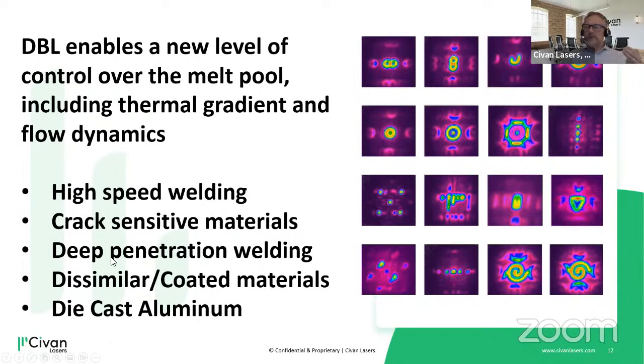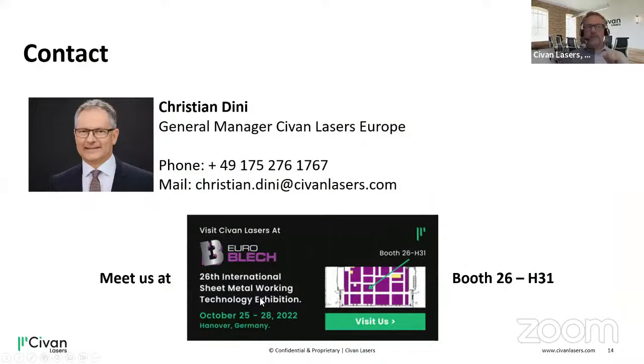We achieve deeper penetration welding in air, so in atmosphere. For the dissimilar coated materials, you have a parameter to directly influence the mixing or not mixing of the two dissimilar materials. And finally, the die-cast aluminum, which is today, at best, with a lot of compromise weldable. But with the control of the outgassing, this is a big improvement as well. And with that, thank you for your attention. And by the way, if you happen to be at Euroblech, then please stop by, come and see us, and then we can talk a little bit less rushed.